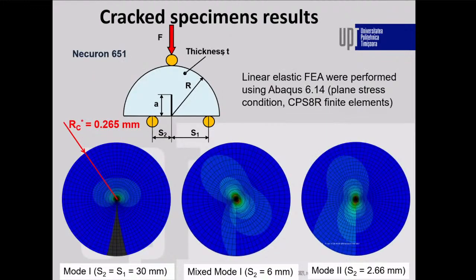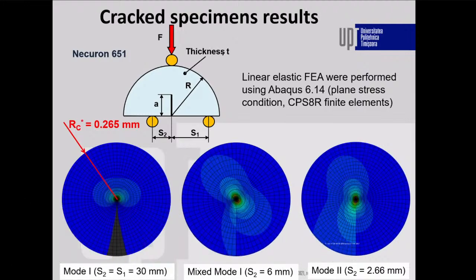Then we performed some linear elastic finite element analysis using Abaqus with plane stress conditions. We used the same control radius for all mixed modes in the first approach. You can see here the distribution of the strain energy density for mode 1, for mixed mode, and for mode 2. This is obtained for this type of specimen only by moving one of the supports: when it is symmetric we have pure mode 1, and going closer to the crack we have mixed mode, and at one particular position, in this case 2.6 millimeters, we have pure mode 2.